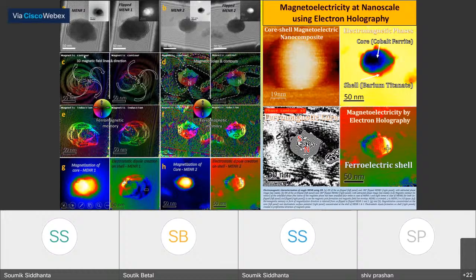But here you can see from this analysis how we can visualize the north pole creation on the particle, and the invisible magnetic field lines in the vicinity of this structure, analyzed through the electron hologram. Again, when the sample is flipped, you can see the south pole in this nanostructure and also the magnetic field lines. But the most important thing in this experiment is that when the top surface was exposed to 2 Tesla, it created a ferromagnetic memory.